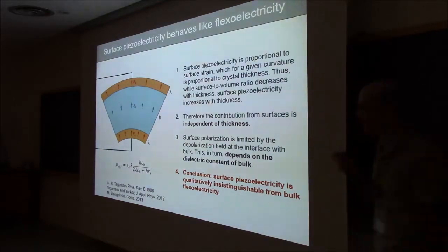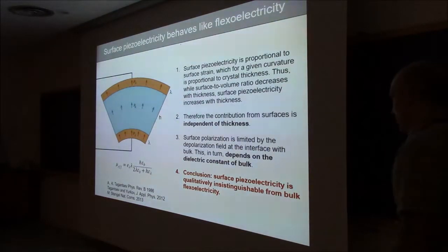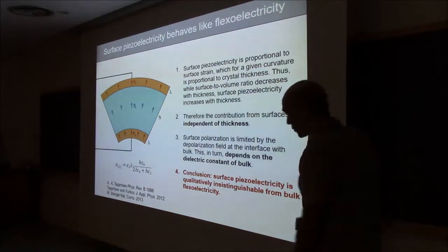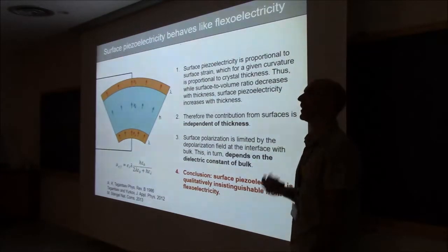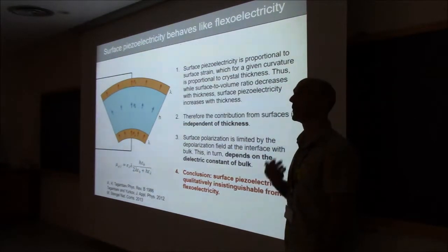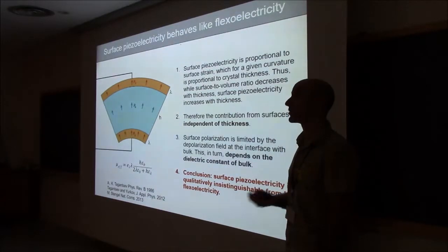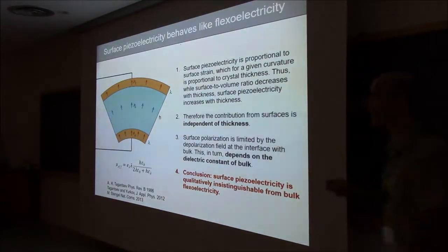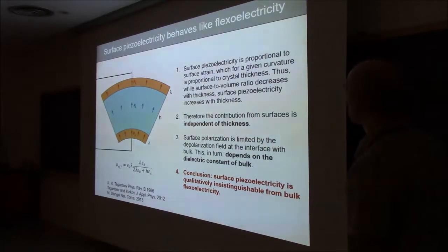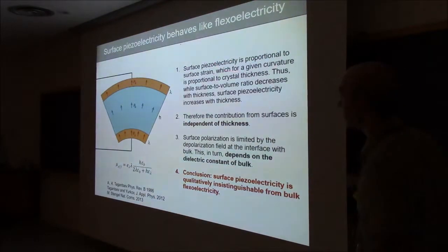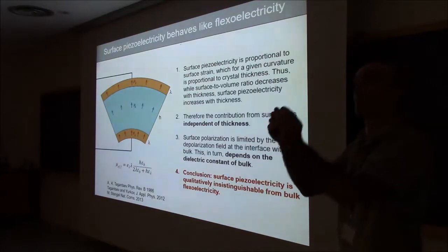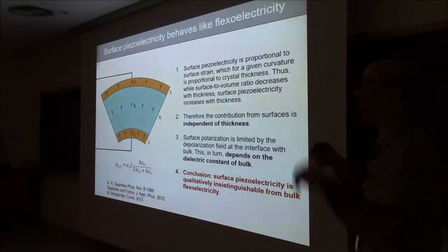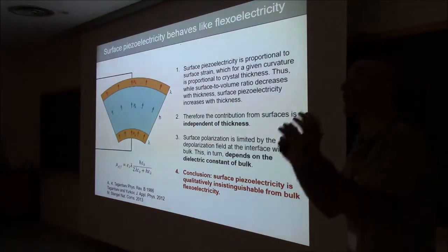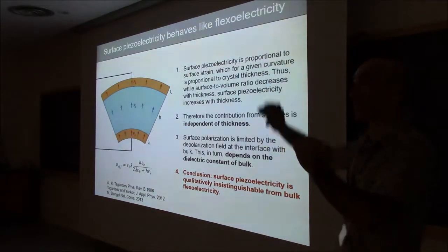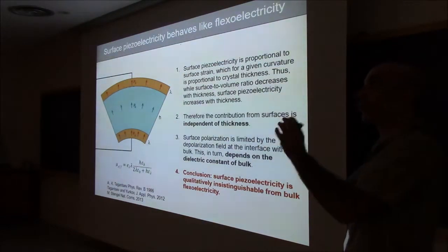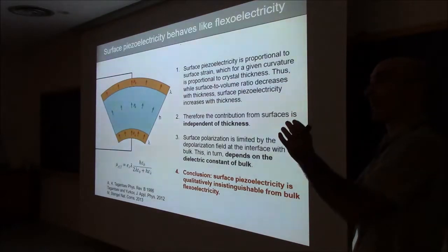Now, this is a real killer, because you might think, or I used to think anyway, that surface piezoelectricity should be negligible for very thick crystals, but it's not so at all. And the reason why you can never neglect surface piezoelectricity is the following. Surface piezoelectricity, of course, is proportional to surface strain. For a given amount of curvature, how much strain you get on the surface depends on the thickness of the crystal. The thicker it is, the more strain I'm going to have on my surface when I bend it.